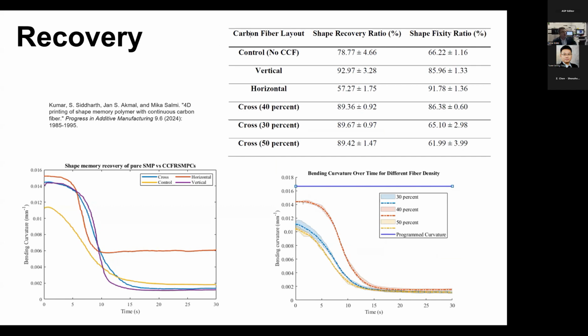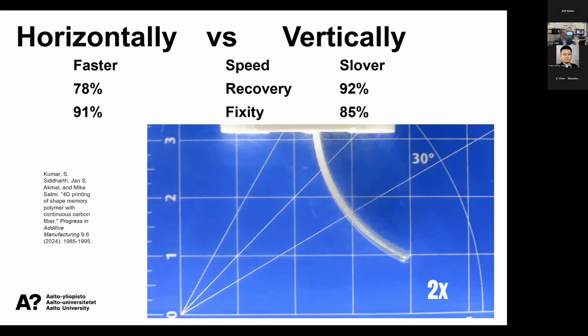So, an example of shape recovery with that geometry: it's about 80% with the control. If you put in the vertical, or having the cross, we can get somewhere in the 90%, which is much better. But of course, if you want it worse, we can put in the horizontal. And here is an example, horizontally versus vertically. The horizontal is faster, but the recovery rate is not so good.